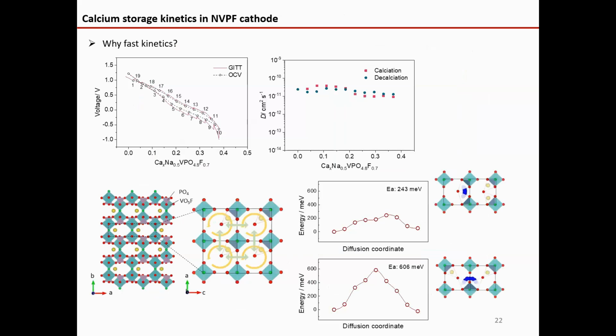And next is why so fast. We conducted the GITT to measure the diffusion coefficient. It's in the order of 10⁻¹⁰ to 10⁻¹¹. It's comparable to the commercial cathode materials in the lithium-ion battery. So it is very, very good.